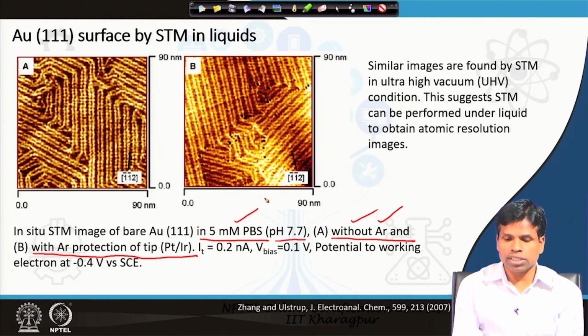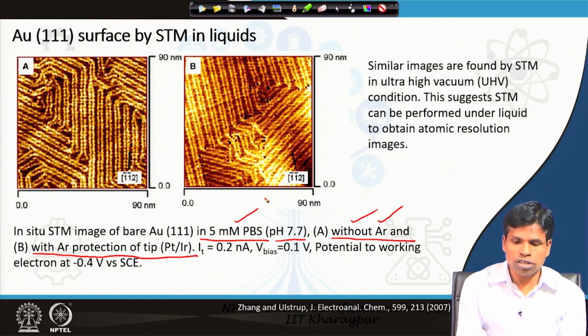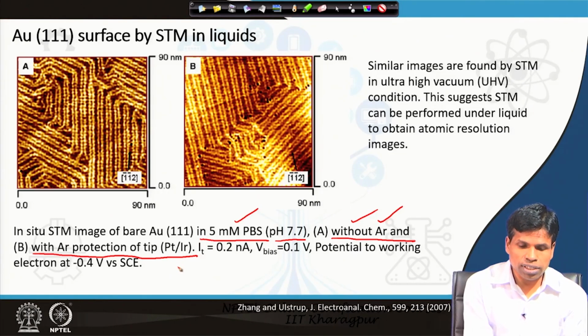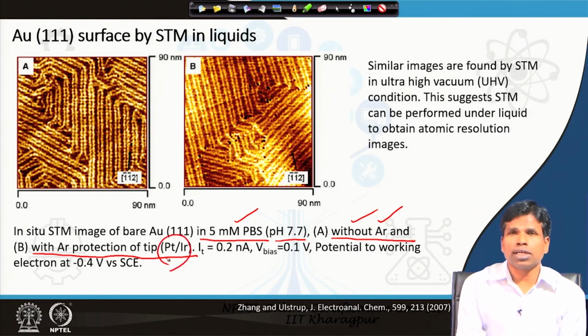So, the oxygen presence in the solution or in the medium has not much impact as far as the quality of the image is concerned. This image was collected using a platinum iridium tip, because platinum iridium tip can be utilized as it is more inert in the solution compared to the tungsten tip, which can form oxide, and once it forms oxide, then the tunneling current measurements cannot be possible because of the low conductivity of oxide.